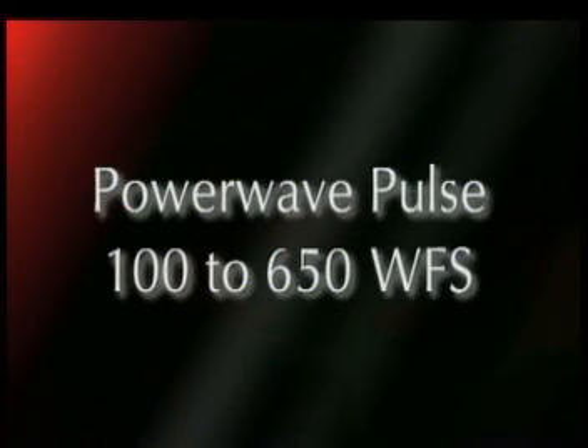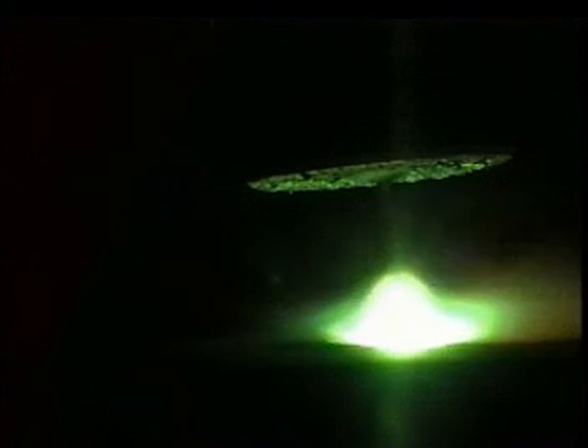Now, let's run the Power Wave in the pulsed mode through the same 100 to 650 inches per minute wire feed speed range. The spray arc transfer mode is maintained across the entire range. No spatter occurs at any point along the range. At the high end, the arc remains stable and does not rotate. Pulse generates a controlled heat input to control distortion and burn-through and to aid in out-of-position welding.